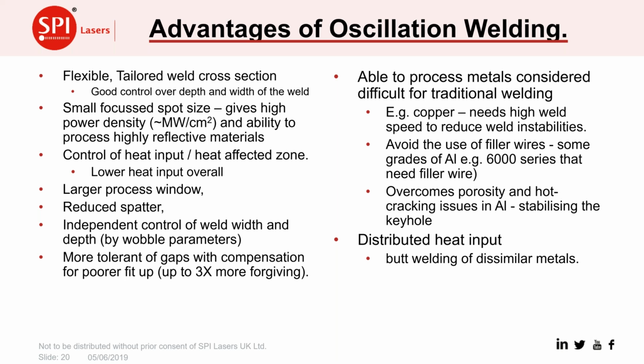And by tailoring the heat input, we're able to look at butt welding of dissimilar metals. We can put more of the heat on the side of the butt weld where the material needs it, and we can do that just by shifting the center of the oscillating pattern. And again, we can tailor the depth through these, even into oscillation welding of dissimilar metals.